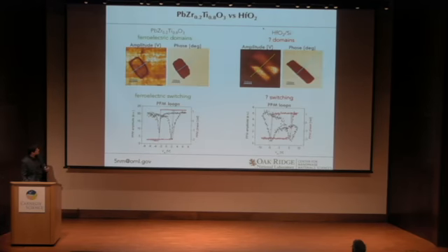So let me start with the first topic, which is contact electrostatics, and this is really to switch or not to switch, right? What you see are PFM images of 2 materials, PZT on the left, and then a thin film of hafnium dioxide on silicon. There's probably little doubt that hafnium dioxide is not ferroelectric, but you wouldn't be able to tell that by just observing these images, even if you zoomed in and spent some time on it, because yes, we can write domains. The domains in hafnium dioxide also have rather good-looking domain walls, and they're not very broad.